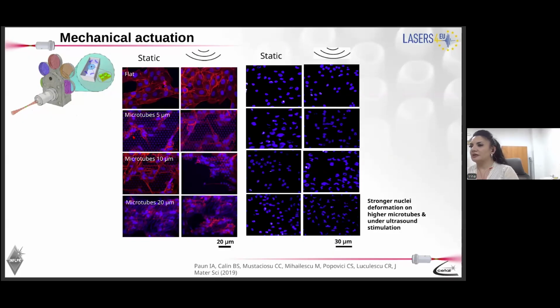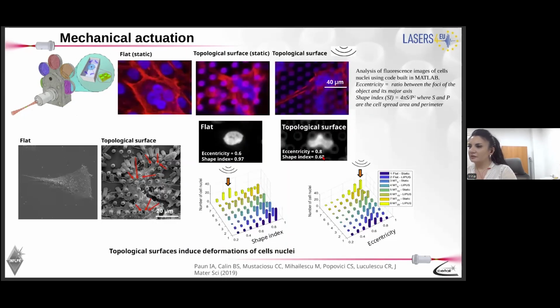And here we extracted from the image on the left only the cellular nuclei to see better what happened with them. What we saw experimentally is that stronger cell nuclei deformation takes place on the microtubes which have the highest height, and which are under ultrasound stimulation. We quantify this effect.